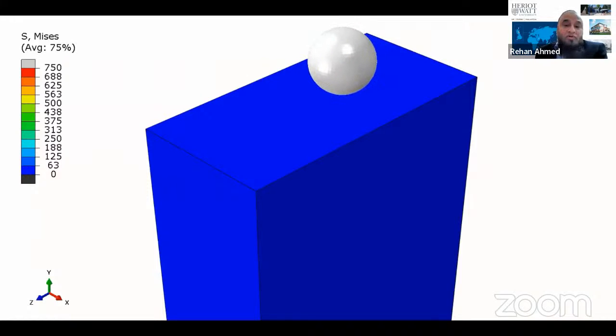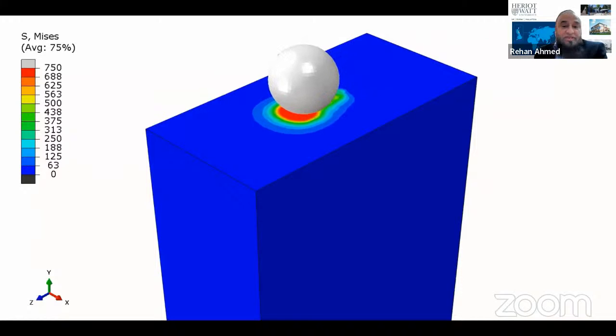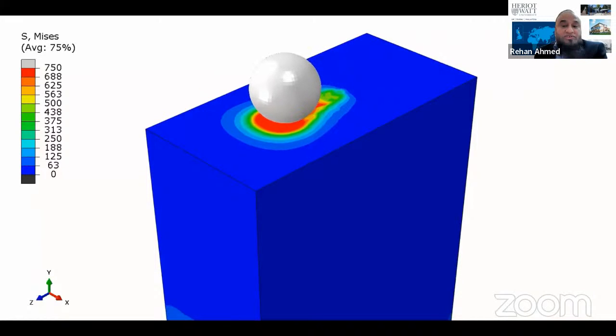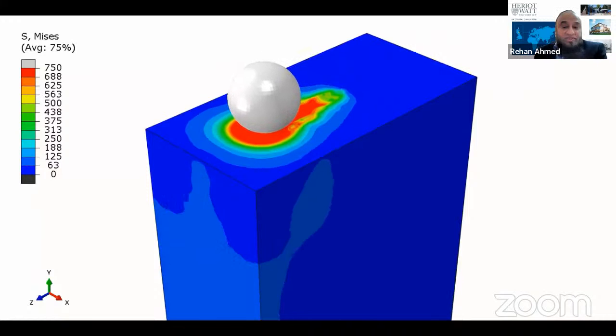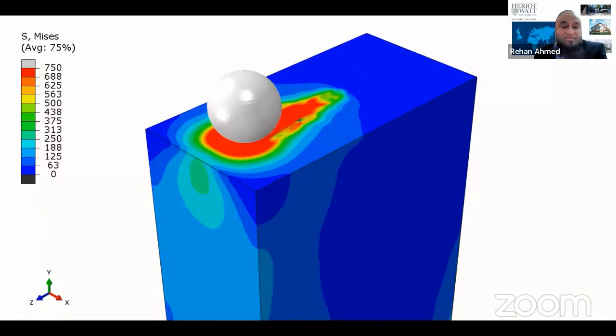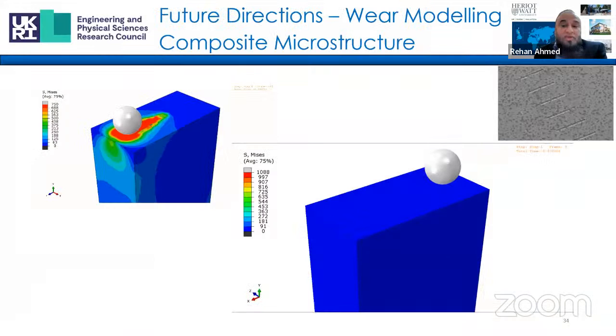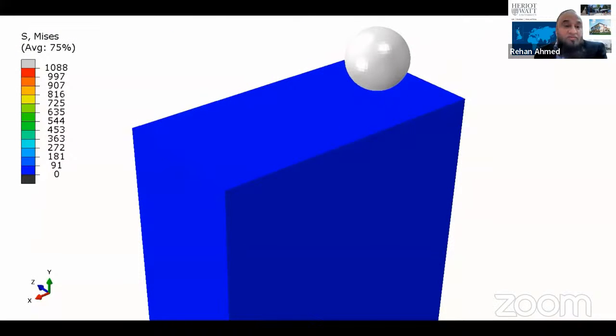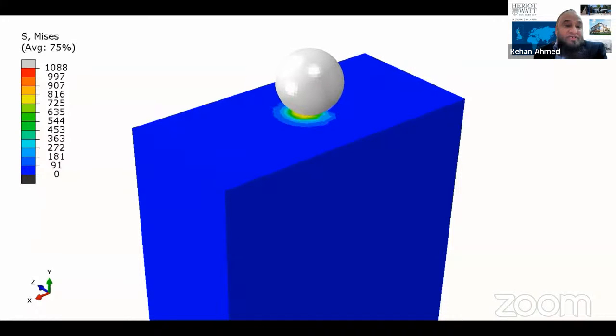We can, however, model the matrix and carbides as two separate phases. And the second video shows how the carbides in the microstructure can be included in the elastic plastic scratch model for composite alloys. So this is the one where we have modeled the matrix and the carbide separately, and the bright red regions, which will appear any minute now, hopefully, will actually indicate the carbides within the material.